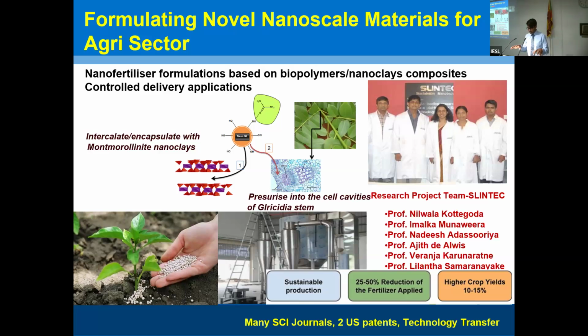And if I explain a little bit how we transform nano-based materials into this particular application, this is the nano composites application or the formulation for nano-fertilizers. So you all know that we are using urea as a nitrogen supplier. One of the key problems with urea is that it is highly soluble, and if you administer urea, it flushes out quickly and ends up in water bodies, causing eutrophication and other environmental problems, and more importantly, economic loss. So we are losing 40%. Our challenge was to come up with a novel system to address this issue using nanotechnology.